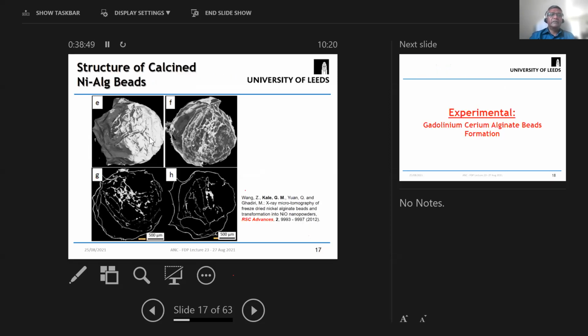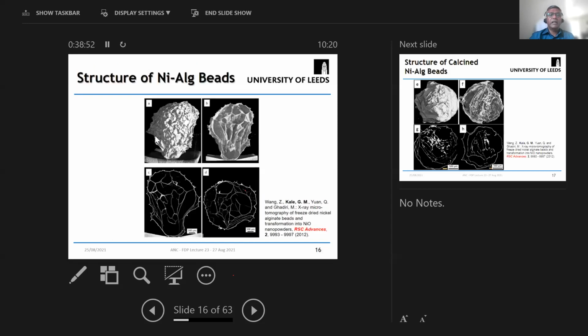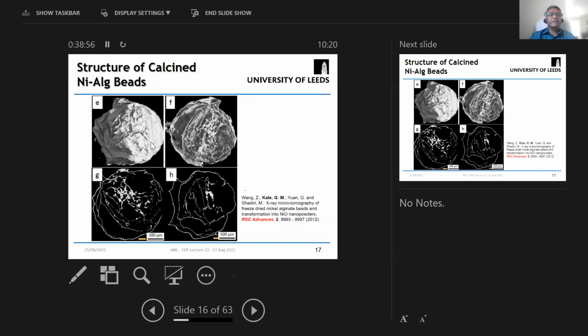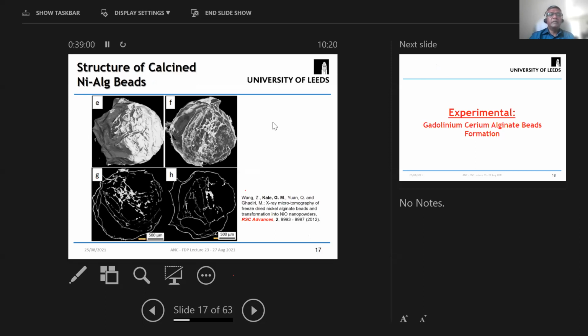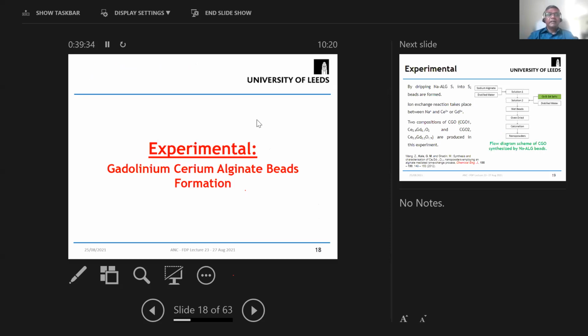This one is the dried bead, the freeze-dried bead, and this one is the calcined bead. So you can see that this is the calcined bead, and the structure of the bead is still retained even after calcination. So this is the calcined bead showing the retainment of the structure. And because the calcination process does not break down the structure of the bead, it still prevents the grain growth between the nanoparticles. Okay, so that was the story about nickel alginate or nickel oxide production.